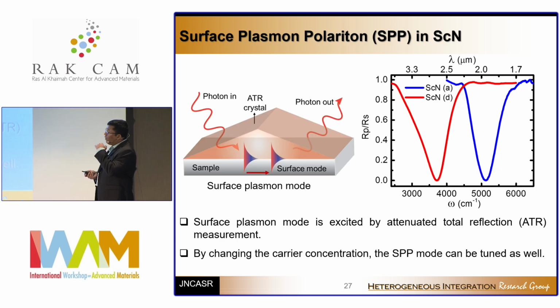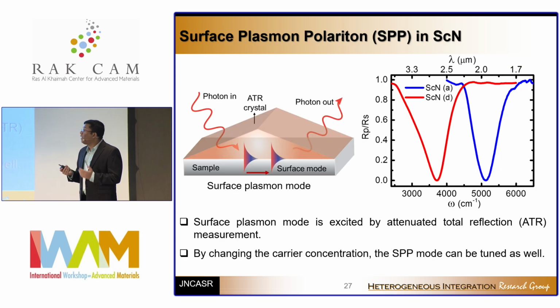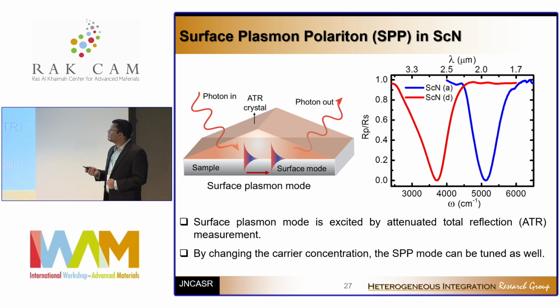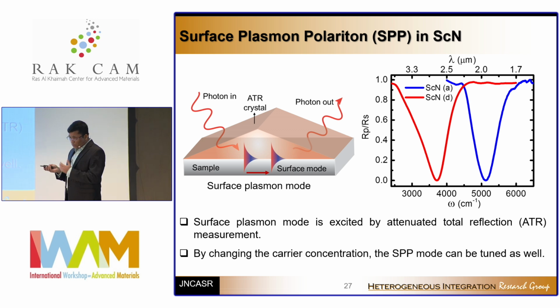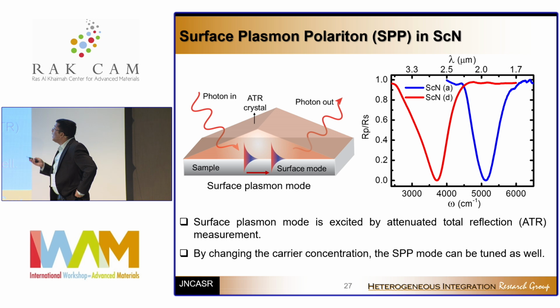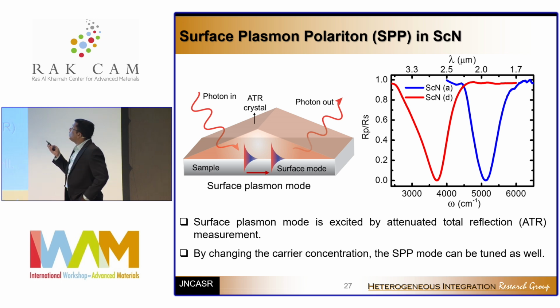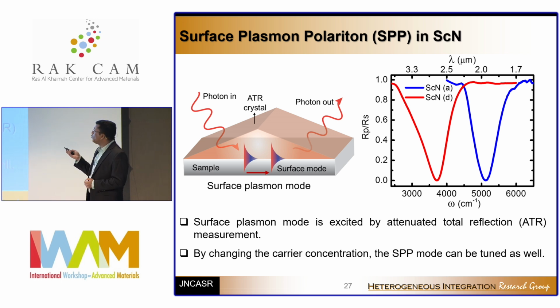Now, along with the excitation of the normal plasmon, we also excited surface plasmon-polariton in scandium nitride by putting a diamond crystal on top of the scandium nitride sample, and you can see this excitation of the surface plasmon-polariton close to the relative plasma frequency.